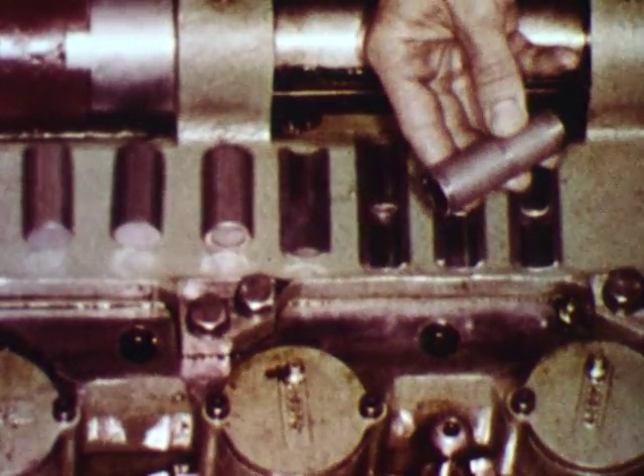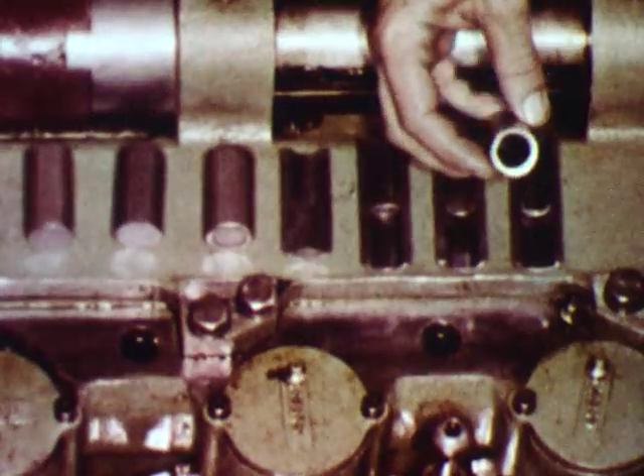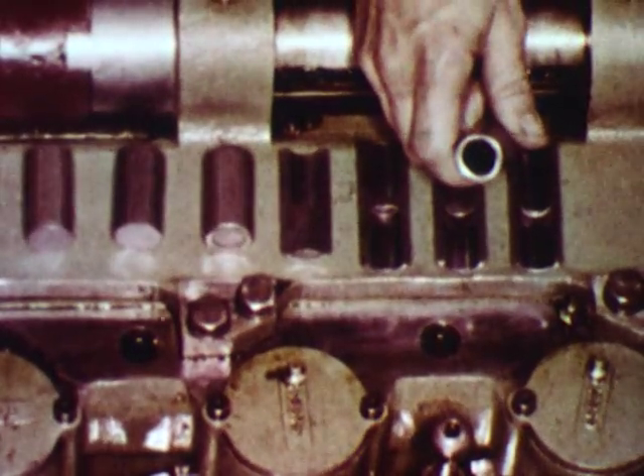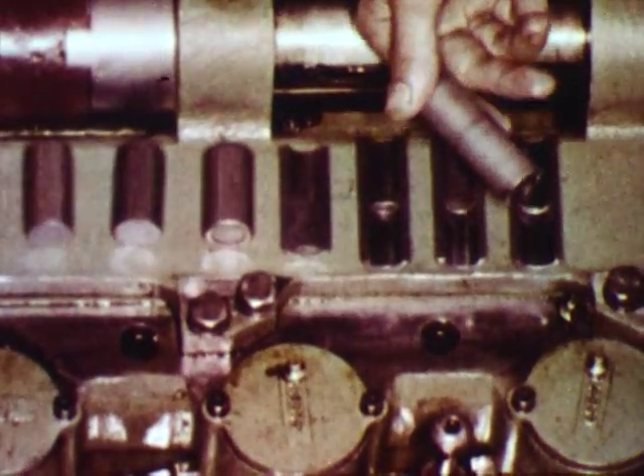The pin is held to very close tolerances. The concentricity is held to 5/1000 total indicator reading, and the length plus or minus 5 thousandths. The close tolerance on the length of the pin is possible because of the accurate cutoff. The die lubricant and coolant is a special extrusion oil.